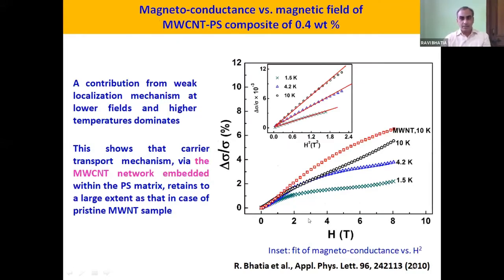Finally, as I earlier said, once you go for low temperature transport studies, with the conductivity versus temperature, you must carry out a magnetoresistance study also, so that you can corroborate the two results and find out whether there is any artifact in the result.